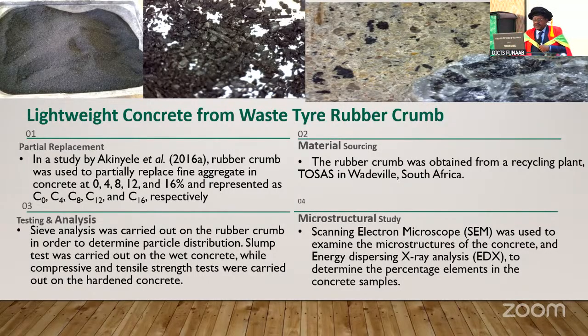The test analysis. Sieve analysis was carried out on the rubber crumb in order to determine the particle distribution, a slump test was carried out on the wet concrete, while compressive and tensile strength tests were carried out on the hardened concrete. Microstructure analysis was carried out using SEM, which was used to examine the microstructure of the concrete, and the energy dispersive, and this determined the percentage of elements in the concrete.